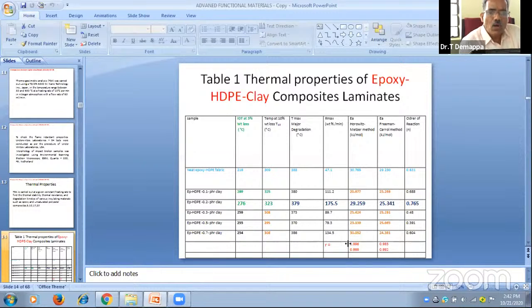These are some inconsistencies. This is because when temperature increases, the oxides of the modified clay will form, and that enhances the degradation. Degradation increases. That's why this is called an anomaly or inconsistency. Whereas for the acceptance of these models, two models were completely accepted because the regression analysis gives 0.996 in the Horowitz-Metzger equation and 0.987, 0.985 in the Freeman-Carroll equation. So both are acceptable.